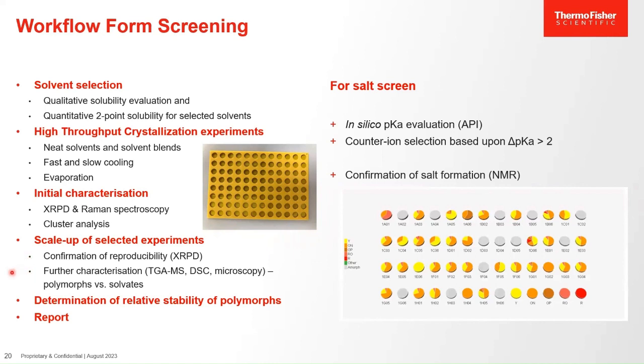And then we carry out further characterization because we need to know whether we've generated polymorphs, whether we've generated solvates, whether we've generated a salt if we're making a salt. And XRPD cannot tell us whether we have done that. It just tells us whether we have the same or different modifications. And we use, for example, thermogravimetric analysis coupled with mass spectrometry to identify solvates. Solvates will become unstable at some temperature, so they will release the solvent. We can identify which solvent has been released with the MS.